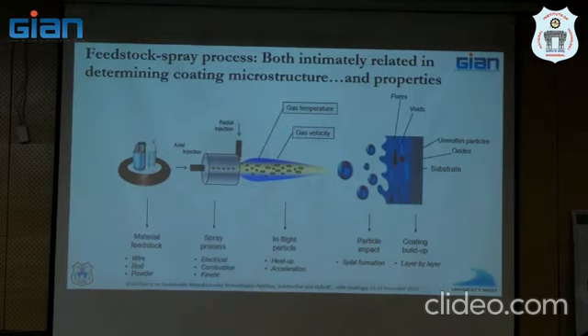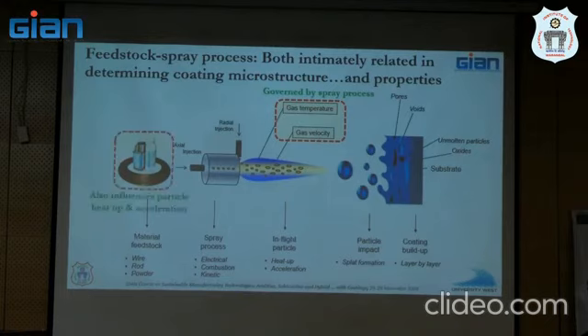But what I actually wanted to talk about here is, what is critical is gas temperature and gas velocity in this region. What is also critical is, from this point on, let's assume that we are using powder, right? What is also important is powder particle size, right? Because both of these together will decide how fast the particle gets heated up, whether it melts or it doesn't melt. It will also decide how quickly the particle accelerates, and therefore at what velocity it will go and hit the surface. Is that clear? So these two, as you can imagine, are the most important governing factors in deciding what happens to the particle before it goes and hits the substrate, right? So when you're optimizing parameters, you're usually playing around with this or with this, correct?